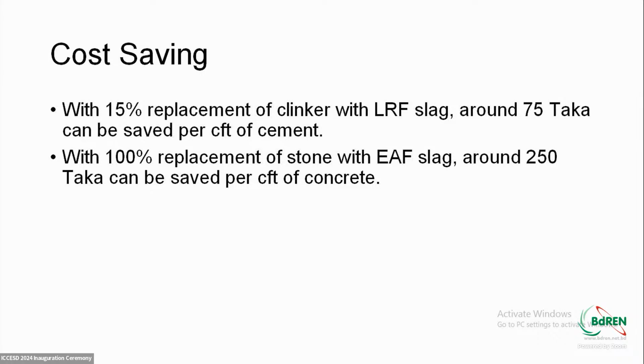Number two, in case of clinker, it can be replaced for cement production, both by EAF slag and LRF slag. But what we suggest is that since LRF slag has no other use, particularly as replacement for coarse aggregate, LRF slag should be used for clinker replacement. And EAF slag can be used as replacement of coarse aggregate, both in cement concrete and in asphalting concrete—in asphalting concrete it's already very commonplace. So we were interested in cement concrete.